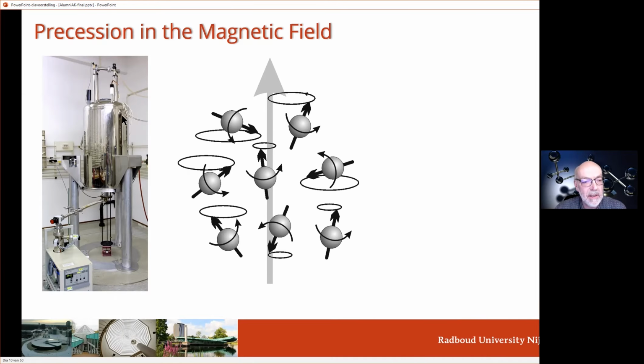So it's essentially a large coil made of superconducting wire. You cool it with liquid helium until the resistance of the wire is 0. You charge it to a certain amount, and then internally you generate a huge magnetic field, which is of the order of a few to up to 28 Teslas these days. Then when you put a sample into the magnet, all these spins precess in that magnetic field, and with their slight preference to be spin up rather than spin down, the energy differences are minute, but there is a slight preference. As a result, the sample builds up a certain macroscopic magnetization.